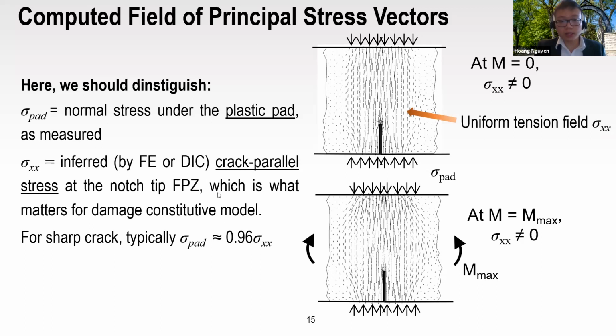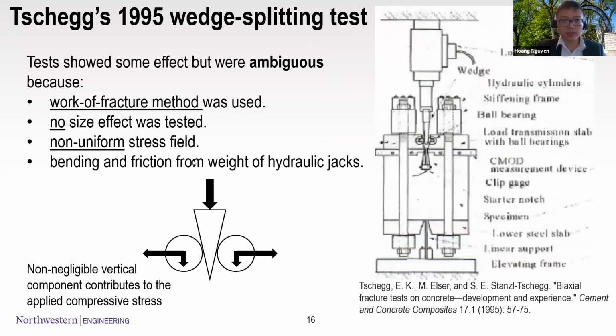And also there's a caveat here because you can see there's a crack, so the stress measured from the pad, which is also measured from the machine, is not exactly the stress here at the tip. So to visualize the real sigma x at the tip, we use a numerical model for that. And we found that the elastic model can give a quite accurate approximation of the real model with the damage. So the elastic solution can also suffice.